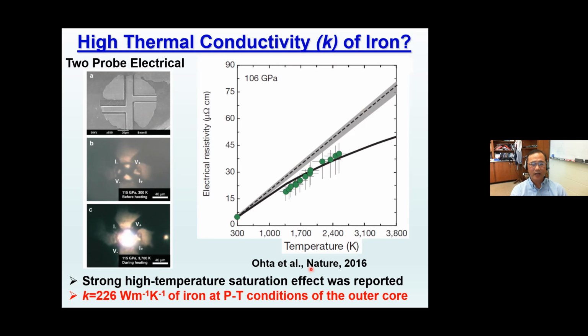Let me use one example here. This was published by Ohta et al. in 2016. Basically, they use a sample geometry like this. I actually call it a two-probe geometry or a pseudo four-probe geometry. And they laser heated a piece of sample. What they found in their results was that the electrical resistivity of pure iron deviates from the more ideal temperature-dependent value here. So basically, that's a temperature saturation. The resistivity does not go up linearly with increasing temperature.